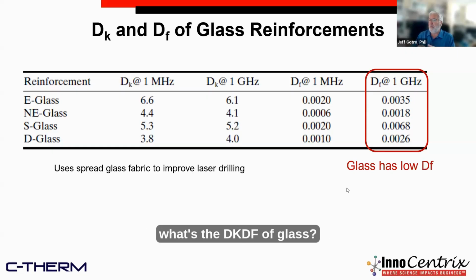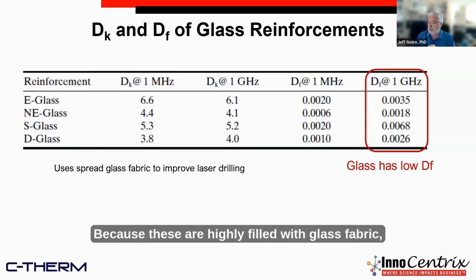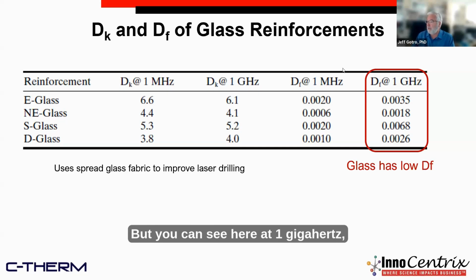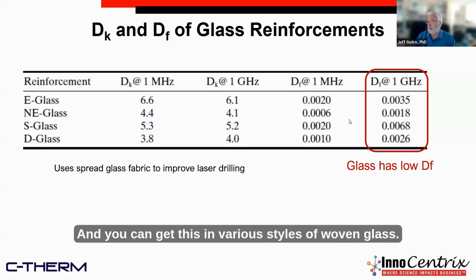The other thing you say, well, what's the Dk and Df of glass? Because these are highly filled with glass fabric, much like you would see in a typical composite application. But you can see here at 1 gigahertz, the glass has a very low dissipation factor. So the good news is you can lower the dissipation factor of the resin, and you already put it in a pretty low dissipation factor glass cloth. So a lot of them use this NE glass because it has the lowest of all of the glass available. And you can get this in various styles of woven glass.